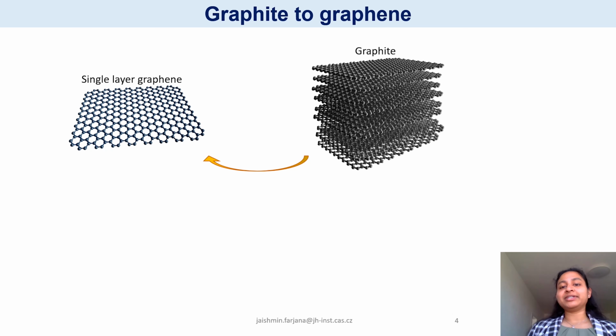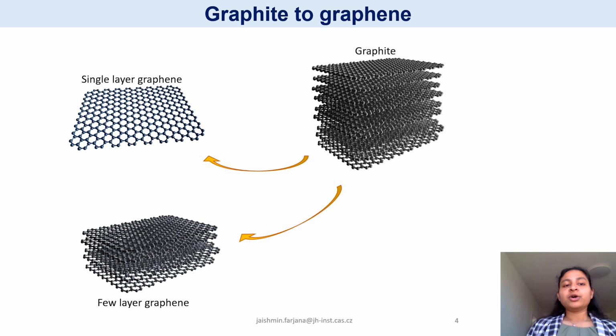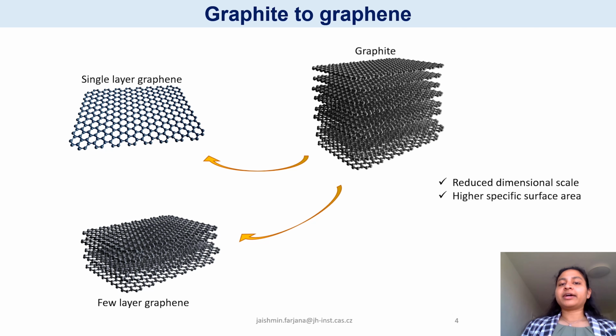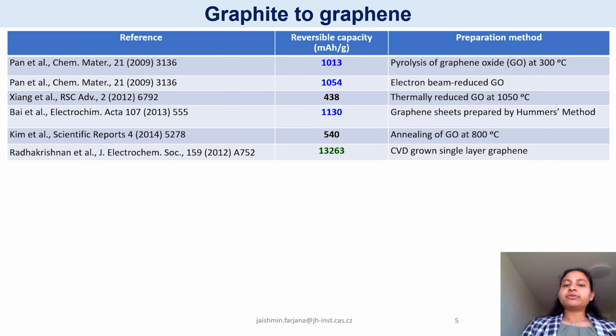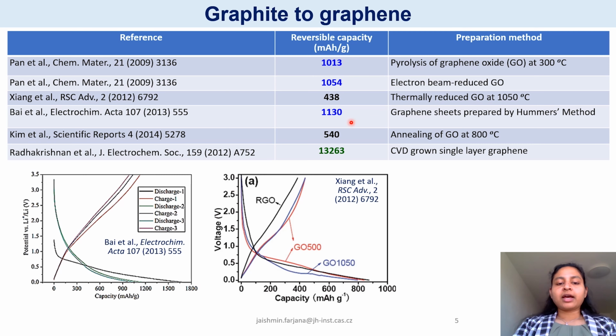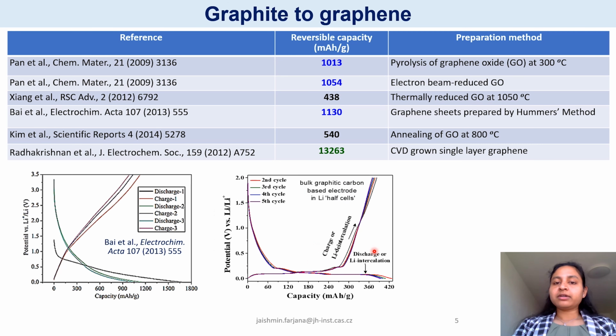And carbon scientists tried reducing the thickness of the graphite to single or few layers of graphene, which is expected to have a higher capacity and also faster charge and discharge. But when it is checked in the literature, we can see that there is a huge range of capacity reported for the graphene materials, and also the potential profile is quite different for this graphene from that of the graphite. So is the lithium storage mechanism different for graphene than graphite? Does the lithium not intercalate in the graphene material? We try to understand that.